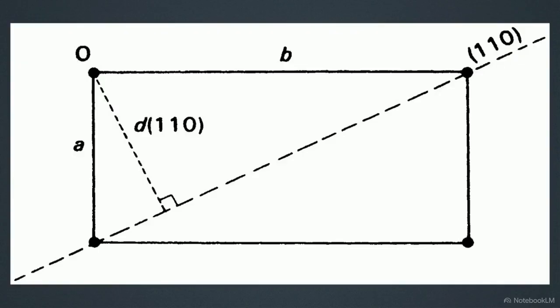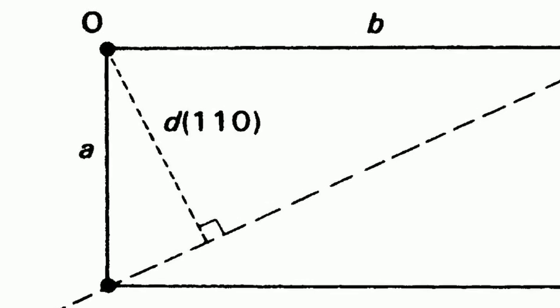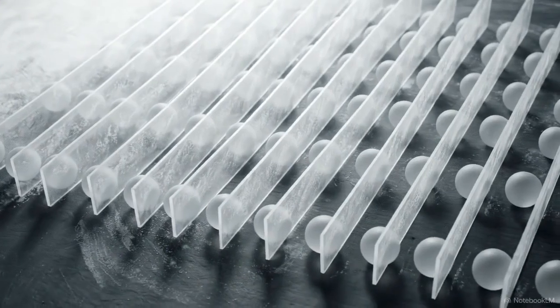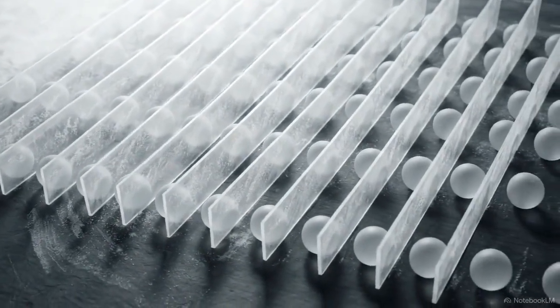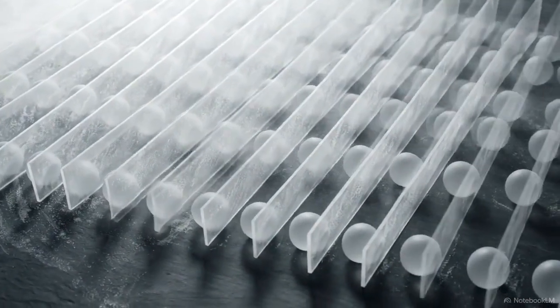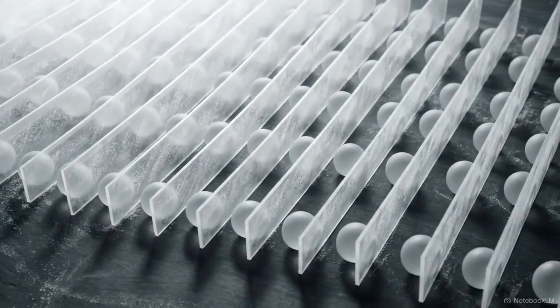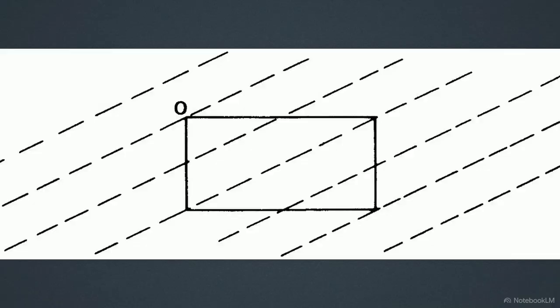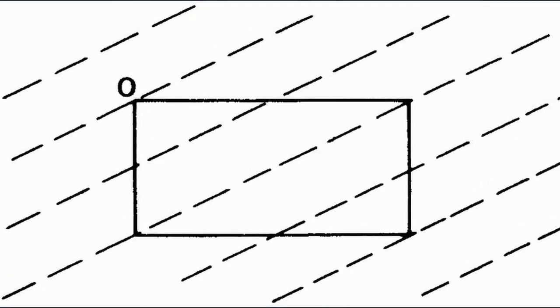This projection shows a single primitive orthogonal unit cell displaying the internal trace of the 1-1-0 plane. We are shifting from the exterior boundaries of the cell to the continuous internal geometry of intersecting planes. By applying the lattice's translation operation, that single plane generates an entire continuous family of equidistant parallel planes, stretching infinitely in all directions. This diagram displays that continuous series of parallel planes, each separated from the next by a precise perpendicular distance denoted as d.